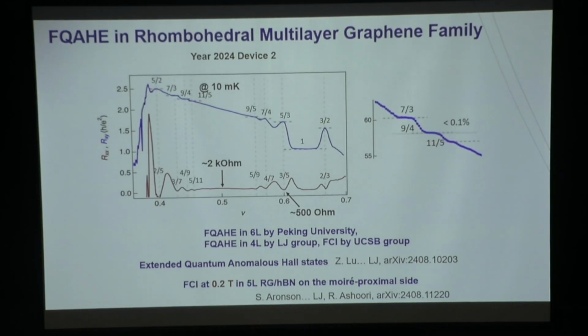We hope with the effort from the community, very quickly we can get it to very close to 0, as what fractional quantum Hall in very high quality gallium arsenide shows. And the quantization of this Rxy is also very good. It's like limited by our noise in measurement. The value of Rxy is within 0.1% of the expected value for all these fractions. So everything is moving in the right direction. And since then, this fractional quantum anomalous Hall effect has been observed in 6-layer graphene, 4-layer graphene, and we have further developments that you're welcome to check if you're interested.